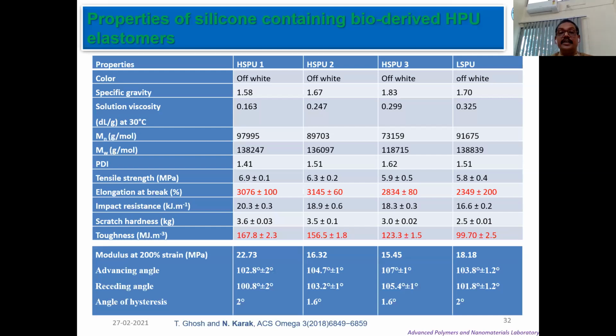So we thought, to improve the property, can we further modify by using some desirable component, like in our last project of DST-CRB, where we had to develop hydrophobic polyurethanes. There we thought that if we incorporate polydimethylsiloxane, which is a low surface energy material, into the polymer, whether the property can be improved. And indeed, we have seen that this material increases the hydrophobicity.